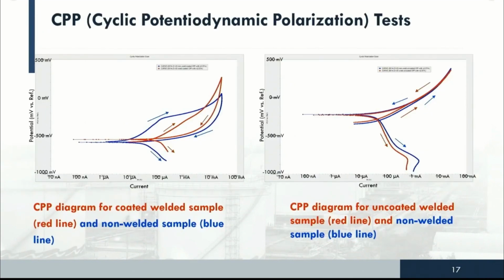The second one, we went into the cyclic polarization, and the one on the left is the non-welded versus the red one, which is welded, and here is the active non-coated welded and non-welded. I'm going to start with this one. It's a typical no passivation, no layer, and an active metal. The welded and non-welded perform the same. Here, as we increase the potential, the pitting current increases, which usually happens for a passive layer. However, if you release that and it goes back into this hysteresis loop, and it cuts slightly under the open circuit potential, this is a characteristic that this layer is susceptible to pitting and crevice corrosion.